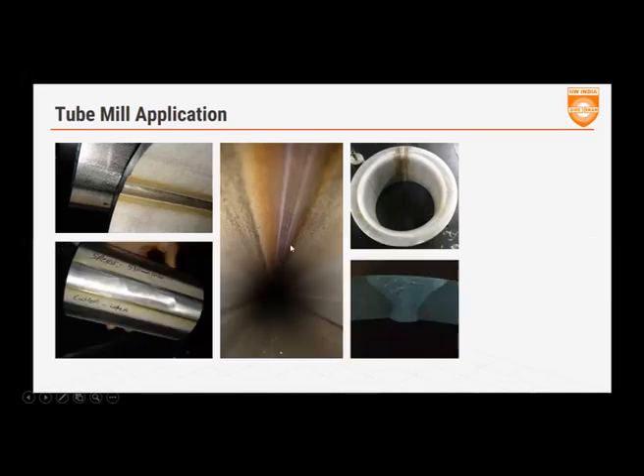Now, if you look at the beads here, these are the kind of bead weld penetration consistency you can get. This we did back to back. About 5 tons of material was produced. Each one of them passed the RTR needs, the flaring needs, the bends, whatever other tests, all are compliant. This is a 5 mm thick pipe, about 5 inches, 530 millimeters per minute on the mill. This is the kind of cross profile you can get.